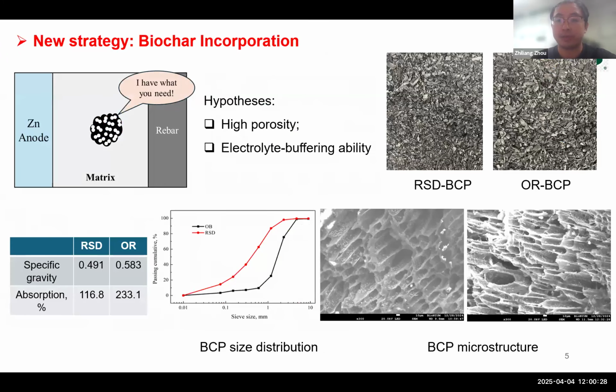In this part of my research, we proposed a new method, which is to incorporate some biochars into this system. The biochar is a porous aggregate. It can not only increase the porosity of the cement-based matrix, but also enables an internal curing effect. In my case, the internal curing effect of a biochar refers to the electrolyte buffering effect. That is, the biochar can store some electrolytes at the initial time and gradually release them to the external environment over a long time.